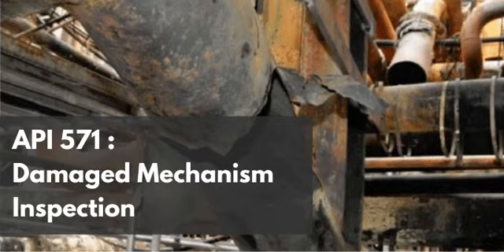Oh, wow. So when a sudden mechanical or thermal stress is applied to the metal later on, the crystalline layers try to slide to absorb the energy, just like they're supposed to. They can't. The alpha prime roadblocks stop the movement cold. Because the sand is in the gears. Exactly. And because the energy has absolutely nowhere to go and the metal can no longer yield, the atomic bonds simply tear apart. You get a sudden catastrophic cleavage fracture.